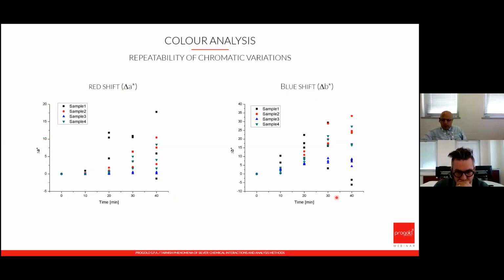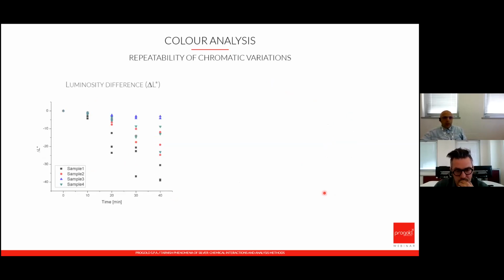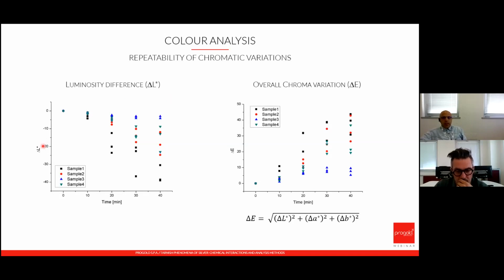And this was also confirmed by luminosity variation and overall chroma variation that simultaneously contain the three pieces of information to define a tint inside the color space, such as luminosity, red and blue components, already watched before as separate attributes. Usually, just to give you some idea of the figure's magnitude, a DE less than 1 is hardly appreciable by the naked eye. And after the sulfidization test, values under 4 can still be considered almost tarnish-free.